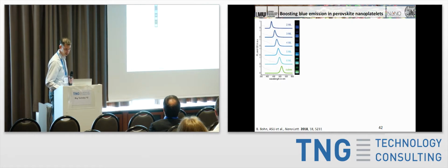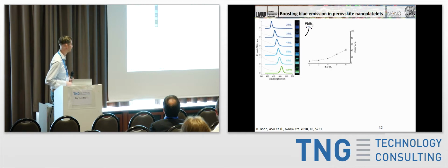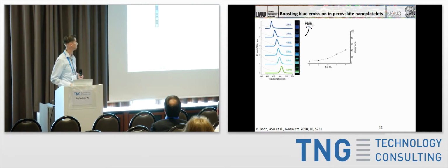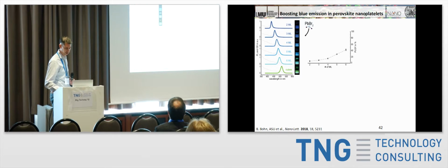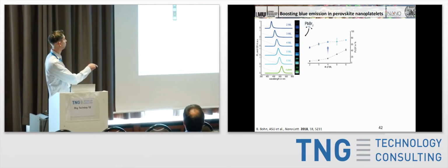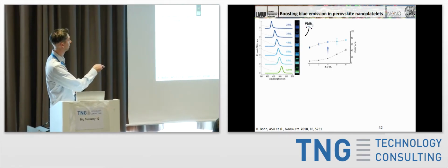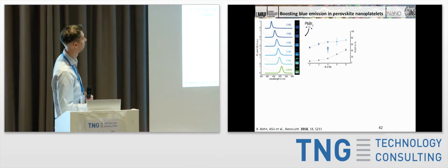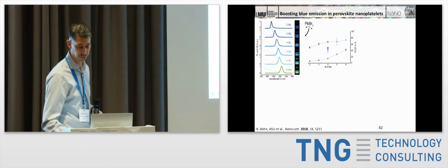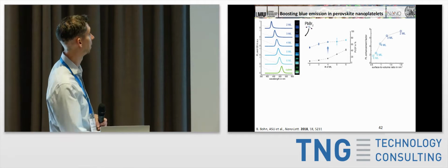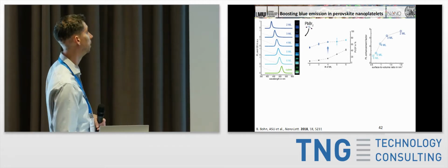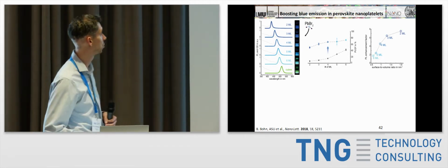And what we found, though, is that we can actually enhance the efficiency of these by adding a second step in the synthesis, by basically adding an extra amount of lead bromide to this. And so we're going from very, very low values on the order of about 5 or 6% for these thin cases to values that are over 50 or 60% in the deep blue. And what we found is that the enhancement factor, so the factor by which the PL quantum yield goes up, is larger the thinner it is.